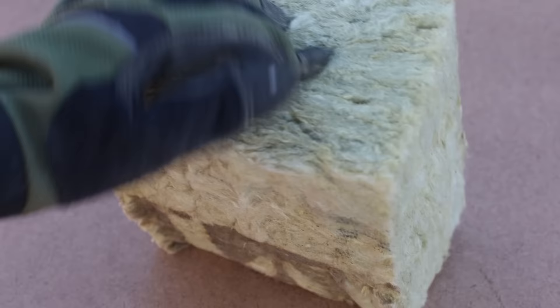Both insulation types operate on the insulating property of air trapped between the fibers. That's why it's recommended to fluff up the insulation after taking it out of the bag. When the bats are compressed, they lose trapped air and the R-value is drastically reduced. The loss of R-value over time is called thermal drift. Stone wool or Rockwool is stiff — if it's compressed, it just bounces back to its original shape, giving it greater dimensional stability and lower thermal drift.